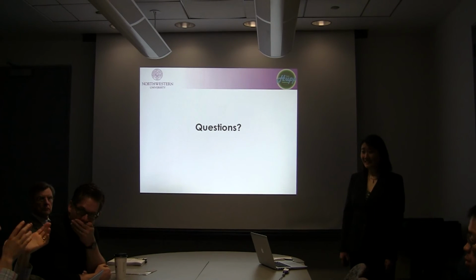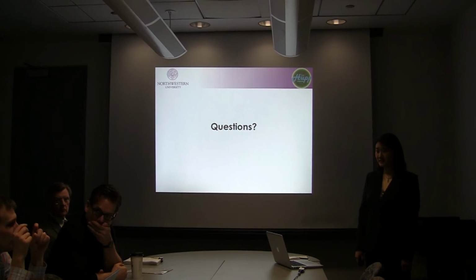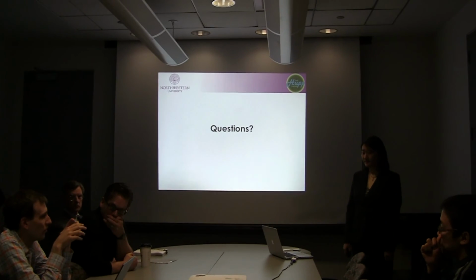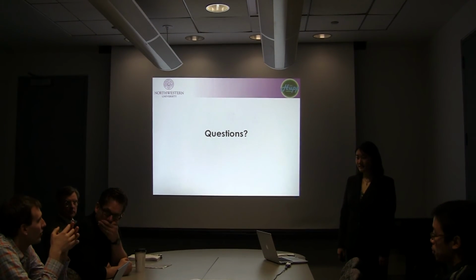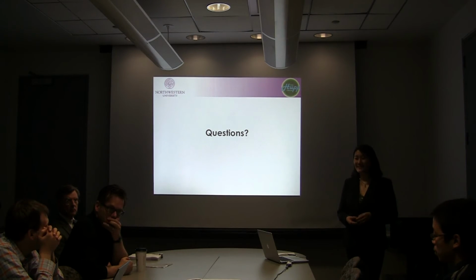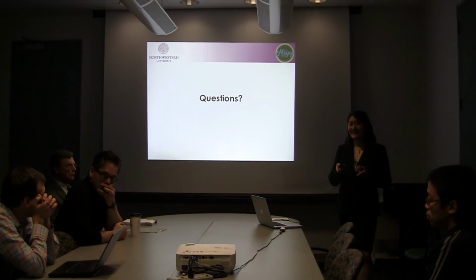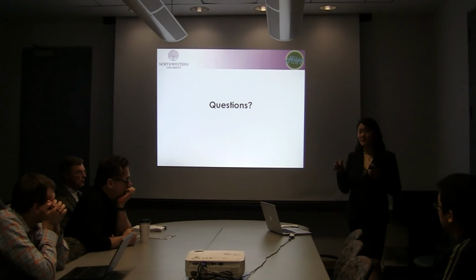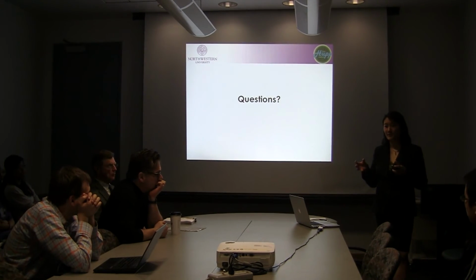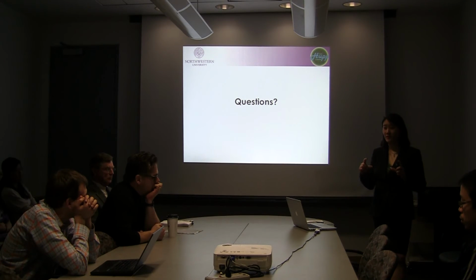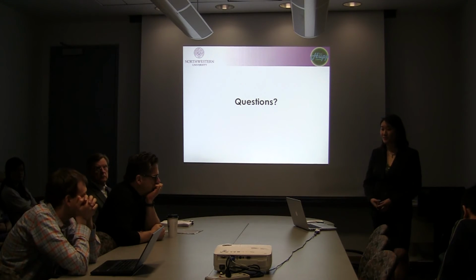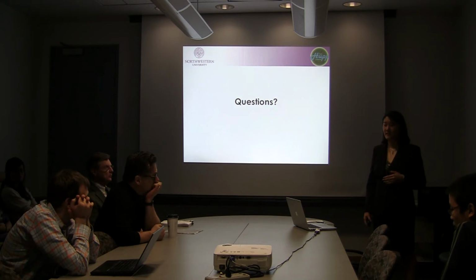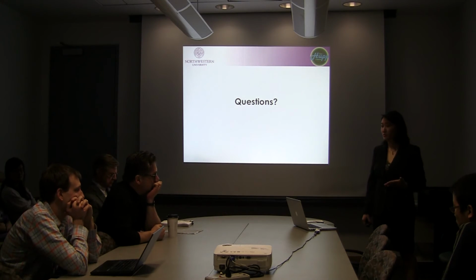Sure. To follow up on the question, would you be able to metallate specific zones? It seems to me your metallation process is a full exchange of the system. So you would have to be diffusion limited or something. Right, so that's why I think depositing pre-magnesiated porphyrins would allow better control for the formation of zones that only contain magnesium and those that don't. That would be more clear, and I could check that with XPS profiling or SIMS profiling